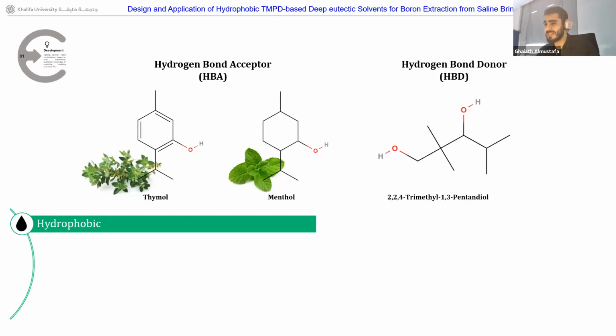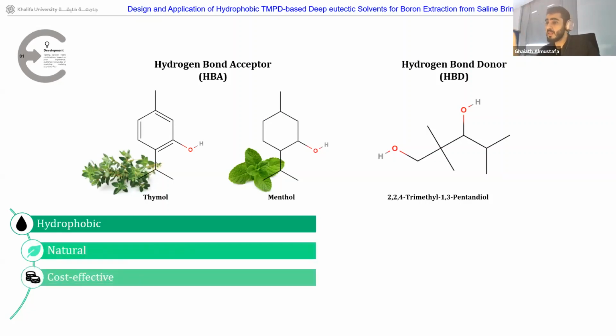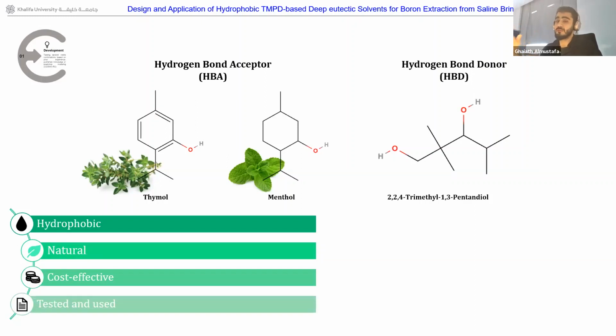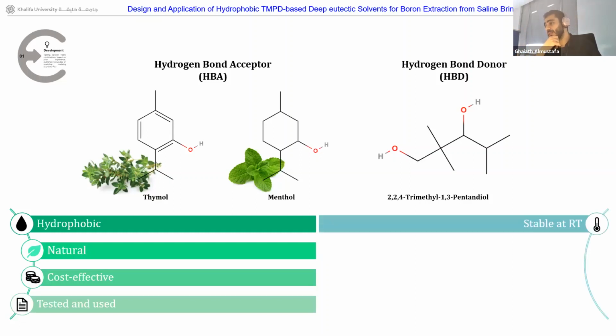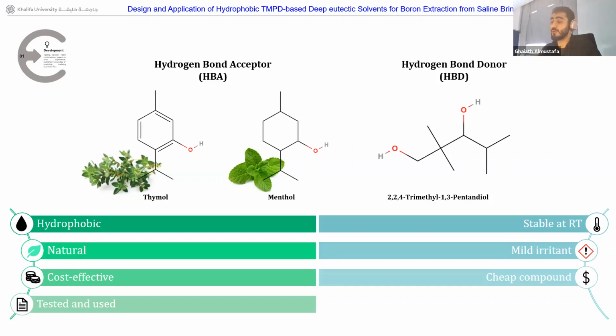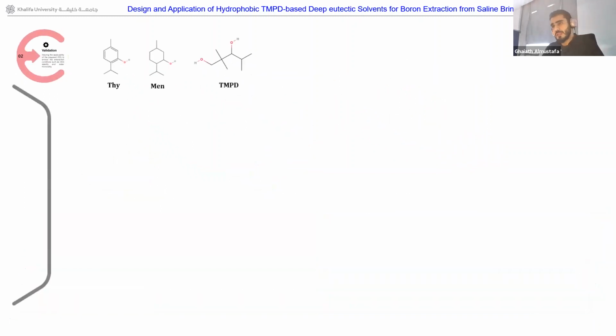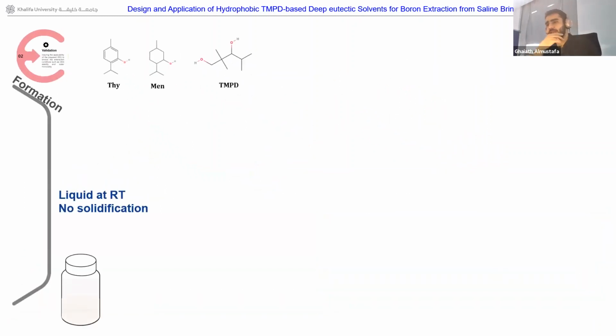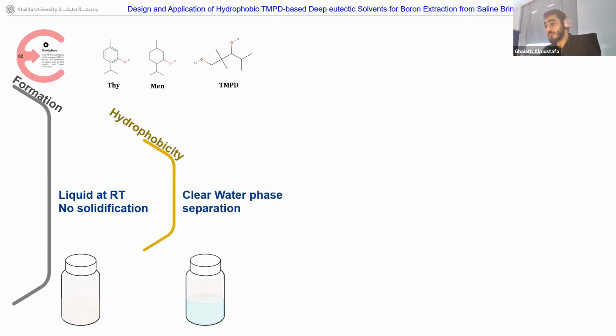Thymol and menthol are intrinsically hydrophobic. They are natural and renewable materials, very cost-effective, cheap materials, and they have been tested before to form very stable hydrophobic eutectic solvents. Likewise, TMPD is a solid, stable at room temperature. It's a mild irritant, with very low toxicity, and it's a comparatively cheap compound, and it has been used before, as I showed. Now, what does the validation step look like? We mix them. It's in 4 steps as well. We first test the formation and the stability of those eutectic solvents at room temperature. And then we test their hydrophobicity because we need to test them for water application.